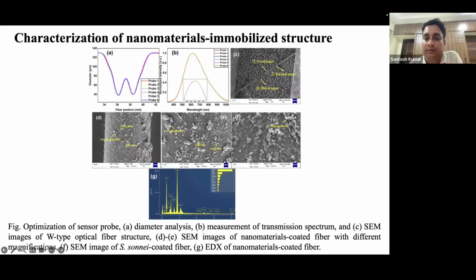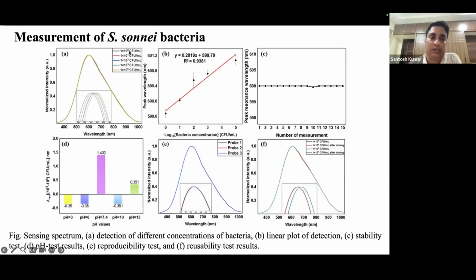Okay, so we have also done the SEM of a Shigella sonnei detected fiber structure, and we can see that bacteria are found on the sensor surface. Okay, so we have from 10 to the power 0 to 10 to the power 5 CFU per ml. We have taken the concentrations and detected with the help of our sensor, and we found that there is a wavelength shift. So through that we have drawn the linearity range, and its linearity is from 1 bacterium to 10 to the power 5 CFU per ml. And we have also taken the buffer solution, and we have measured 15 times, and we found that the standard deviation is quite low, and the stability of the sensor is quite good.